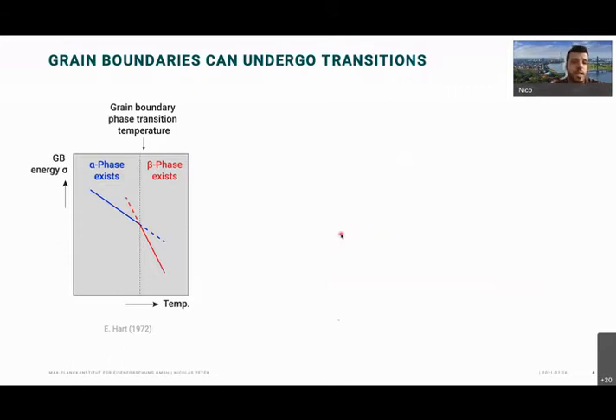Now there's a concept that has been exploited by Hart already in the 70s, who said, well, a grain boundary can also undergo transitions. So he postulated that if you look at the grain boundary energy versus the temperature, you will have at room temperature an alpha phase that exists of some sort, whatever it is. And then if you increase the temperature, at some given temperature, you might change to a beta phase. So the grain boundary itself undergoes a transition, basically. And this transition can have multiple facets, so to say.